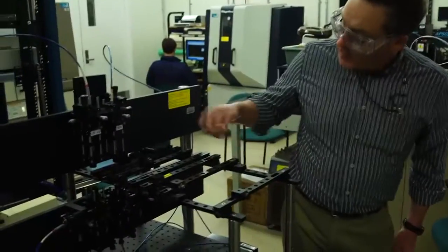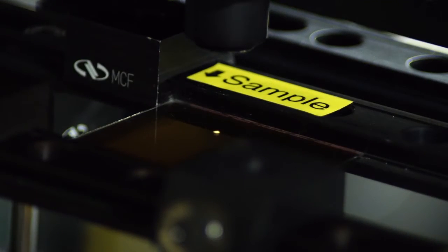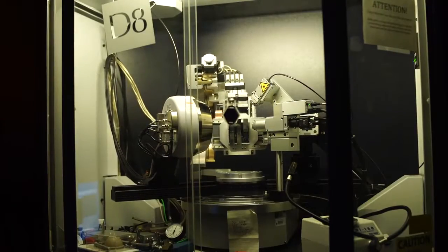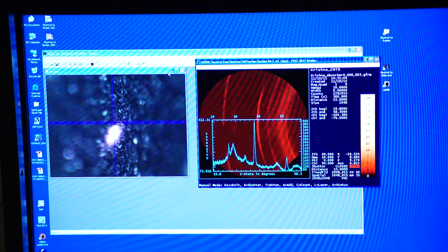We're looking at things like atomic layer deposition, pulsed laser deposition, hydrothermal synthesis, solution chemistries, and sputtering — each of these different techniques provides something different and allows us to change a different range of parameters so we can access a lot of these high-energy polymorphic structures. By understanding how things start and through the whole process, not just the two end points, we can better understand that reaction and make more informed decisions about the materials we're trying to target.